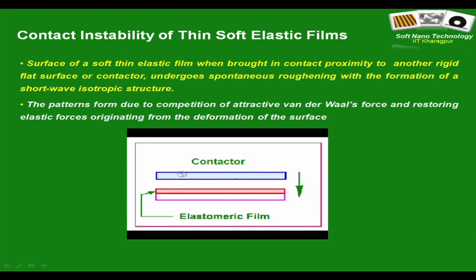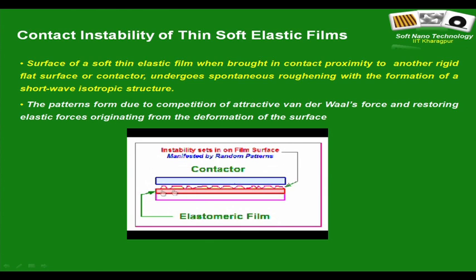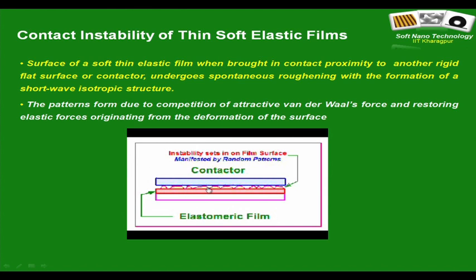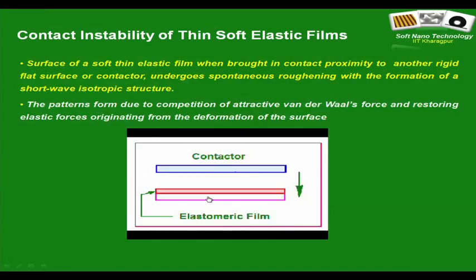So you have a contactor which is coming in contact with a flexible soft elastic film, and before they come in complete conformal contact, there is a zone where the separation distance between this film and the contactor is again in the range of that 100 nanometer bracket. Therefore, there is active van der Waals interaction between the two, and that leads to some sort of self-organized instability structures on the film surface.